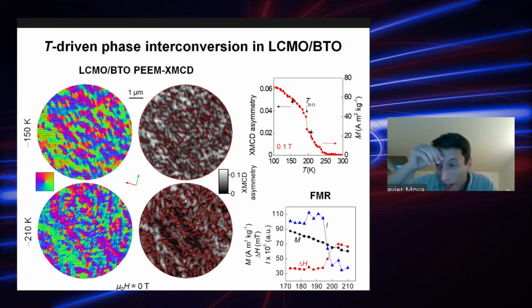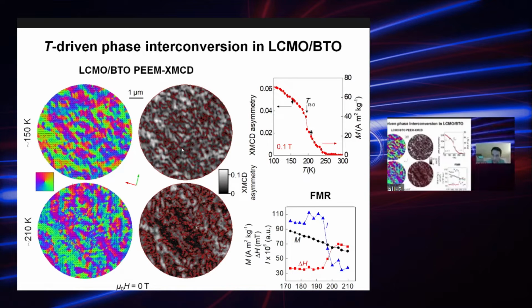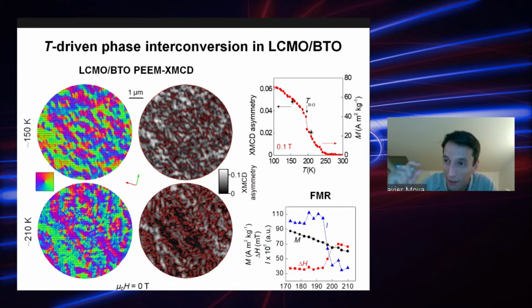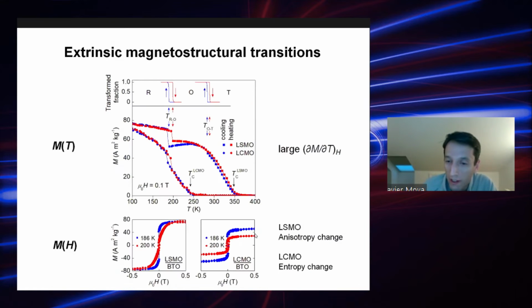LCMO is known to have phase separation, and this phase separation is modified by strain and by stress. So what happens is that in the high temperature phase, the LCMO is quite phase separated into ferromagnetic and paramagnetic regions, and then when you drive the transition in the substrate, the film becomes mostly ferromagnetic, and this gives you this big increase in magnetization across the transition.